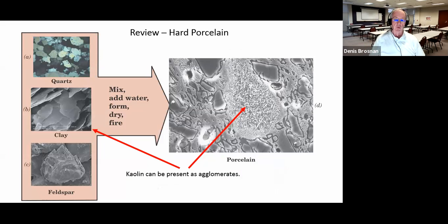Last time we talked about porcelain products, and these were really highly vitrified ceramics containing up to about 30% glass or thereabouts. The triaxial porcelains were made of crystals or granules of quartz, typically minus 200 mesh ground silica called potter's flint. Clay, typically kaolin, which served the function to provide a binder in the shaped product and also provide mullite. And then there's feldspar, which is a major component to forming that large amount of vitreous phase.